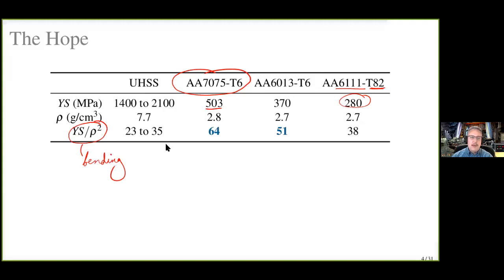And when we do that, we see that the ultra high strength steels are somewhere around here, where the 7075-T6 material has potential to double the efficiency of use for mass savings of ultra high strength steels. Even a high strength 6000 series, which would be kind of a moderate strength aluminum compared to all the possible aluminums, even that still does quite a good job. So the question is, how do we begin using this material?